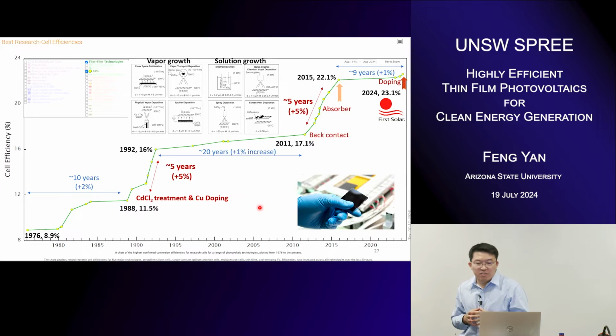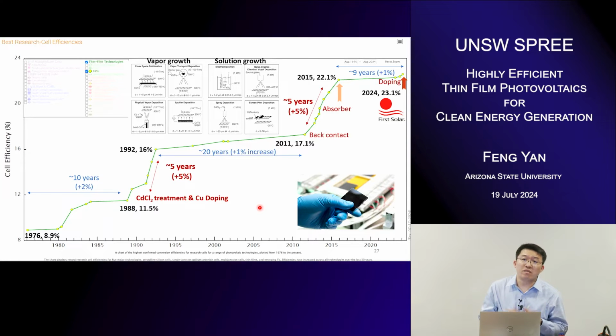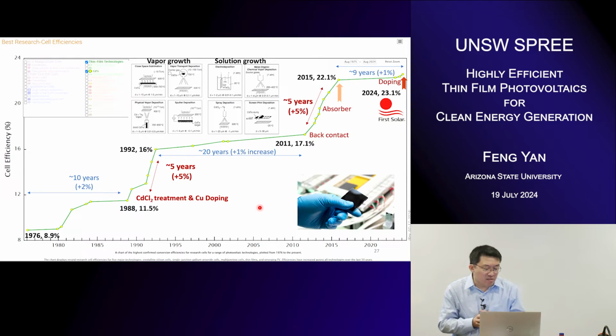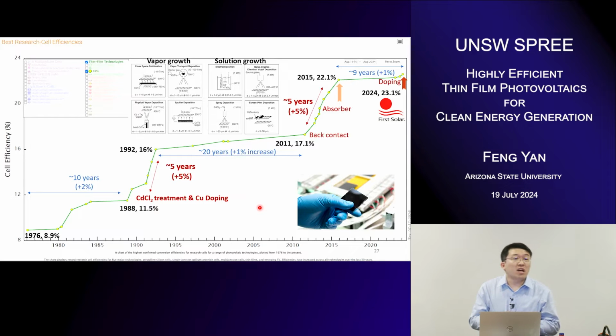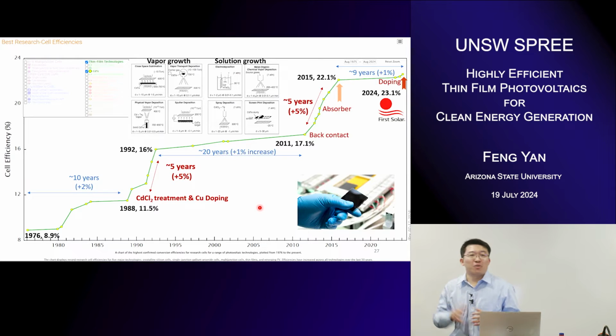Here is the efficiency chart for roughly the past 50 years. You can see that efficiency growth is very challenging for this technique. Initially, it was single digit, back in 1976. It was roughly around 9% efficiency, and stuck there for 10 years before jumping to around 11.5%. More and more techniques and innovations were introduced and boosted the efficiency. The last one, around 16%, was around 1992. That's more than 30 years ago. It stuck there almost 20 years, with just 1% efficiency improvement. So I think most of you do not want to work on this one because you probably cannot graduate.